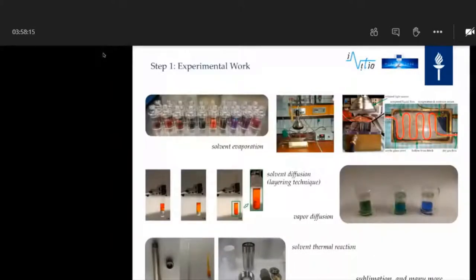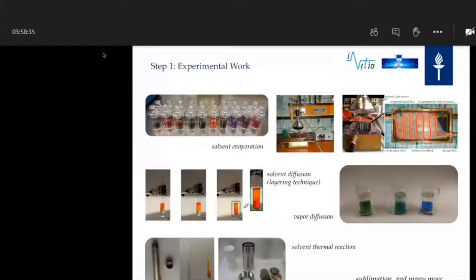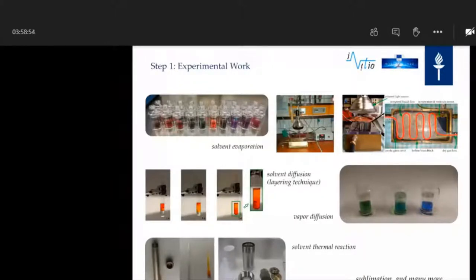So how do we start with experiments? We do a lot of crystallization work. We use different techniques — the most common being solvent evaporation, usually under air at room temperature, but also at lower temperatures. If you use solvents with high boiling points or low vapor pressure, you can also use an apparatus with controlled vacuum to crystallize your compounds.